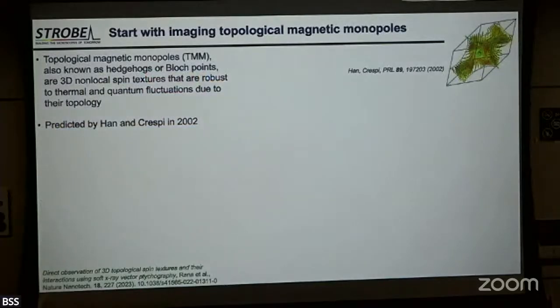So we started on a simpler topologically protected material than skyrmions. It had been predicted by Vincent Crespi and Han back in 2002 that if you made a frustrated magnetic system out of magnetic nanodots, where the dots were connected and their spacing was on the order of the exchange length, that should freeze in some magnetic texture that should be topologically protected. And they call these hedgehogs and anti-hedgehogs.